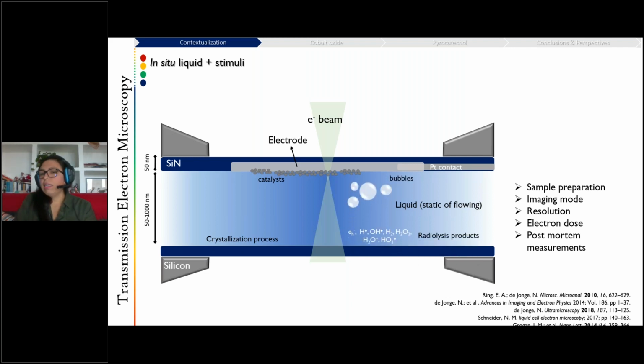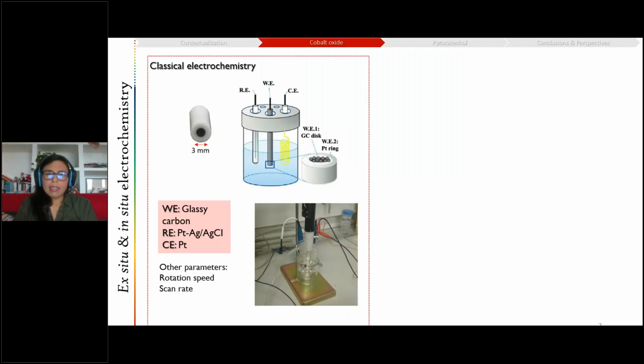The different things can happen, as I was telling, due to the interaction between the beam and the electrolyte and the material: the formation of bubbles or the radiolysis products, also the effect of the flow within the chamber. But we try to overcome all of that to observe the material. And I think it is important to take into account that this setup, of course, will be different from a classical electrochemical cell where typical materials are tested to evaluate precisely that overpotential that they can present.